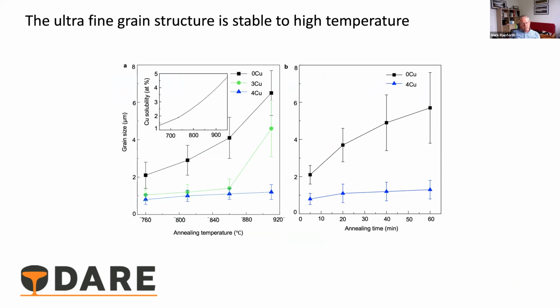And one thing we found is that this microstructure is really very stable to high temperature. So we're plotting there the 3 different alloys. The black is for 0% copper, so the baseline material. The green is 3% and the blue is 4% copper.